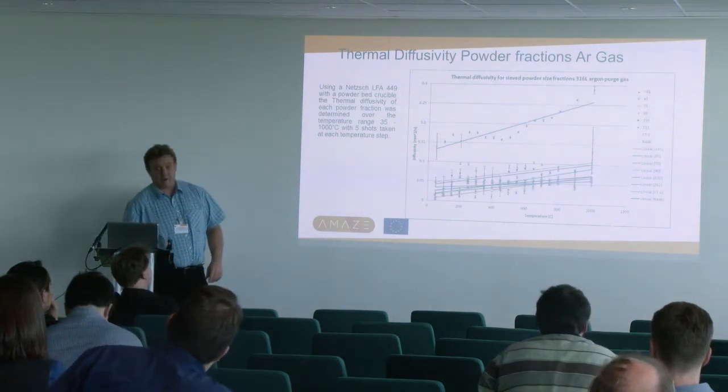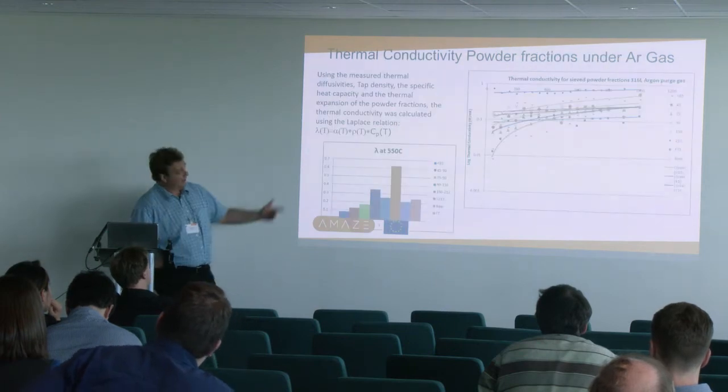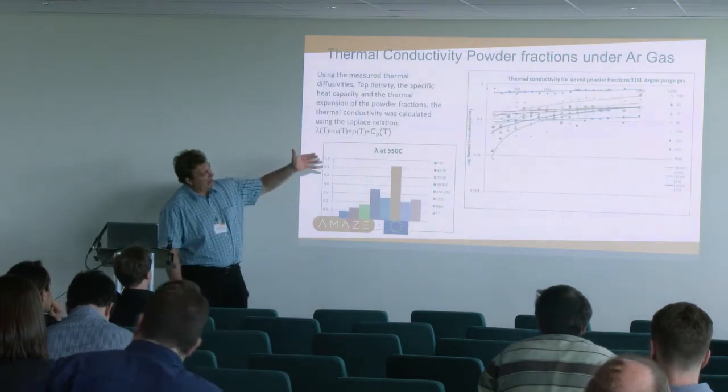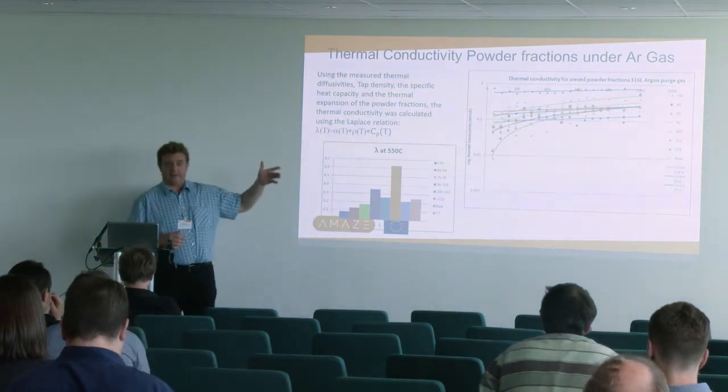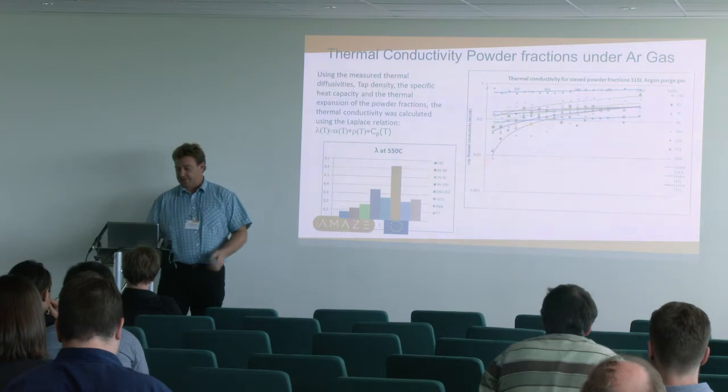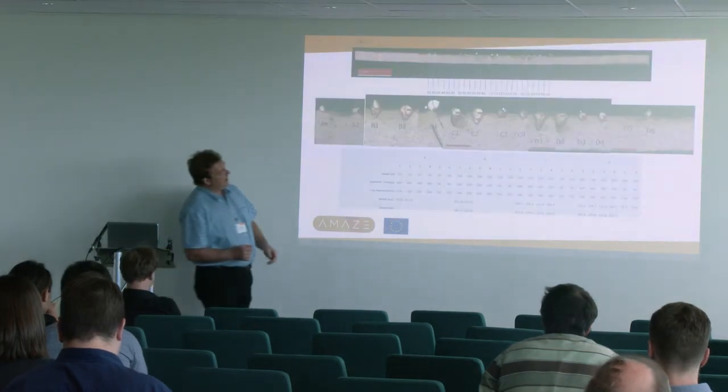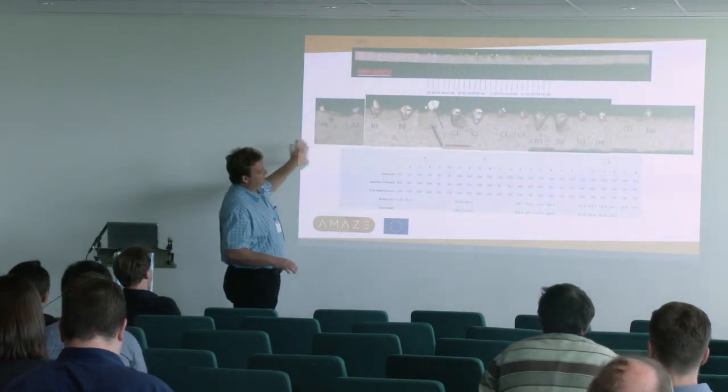So we're using some of the equipment we have, laser flash analysis, to get thermal conductivities. And you can see the very low thermal conductivities, but they do make a difference. There are differences between different powders and different size fractions of powders. These are our own experiments now on the machine, a similar sort of setup.